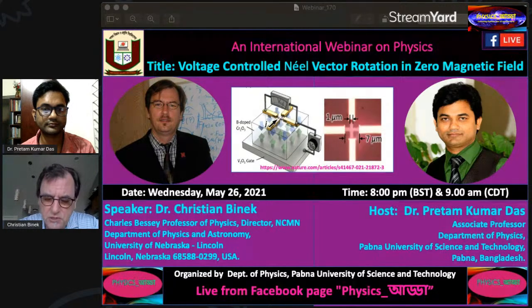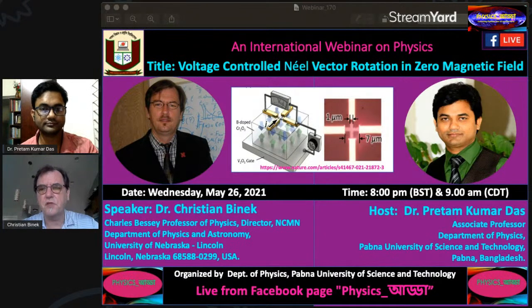If you would measure the hysteresis loop of the ferromagnet when it interacts with the antiferromagnet, you would find that the hysteresis loop is shifted by a certain magnetic field out of the center of the coordinate system. That shift is called exchange bias, and the magnitude of that field is called the exchange bias field. Now, as the name suggests, if you apply a voltage across such a bilayer structure, and if your antiferromagnetic material is very special, of the type I investigate, then you can control that shift. You can move it from the hysteresis loop shifted to the left to the hysteresis loop shifted to the right. And that's what we call voltage controlled exchange bias.